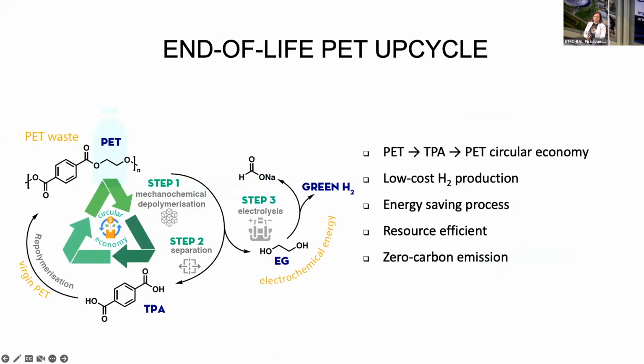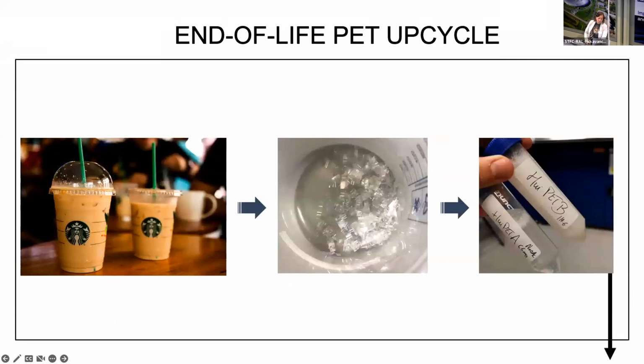Now, inspired by this, we are also working on PET recycling. What we do here is take PET and put it through a sonochemical, mechanodepolymerization process. In fact, we are making, with really high selectivity, terephthalic acid, which is the monomer to make PET, and we're making ethylene glycol. Ethylene glycol is a very similar molecule to glycerol, so we are also putting this through an electrolyzer to produce green hydrogen. We're very early stage, but we've managed to make ethylene glycol from this. So this is a way of turning plastic waste back into its monomer and hydrogen with some mechanochemistry and some electrochemistry. This is quite exciting.